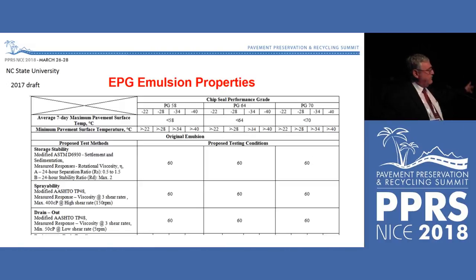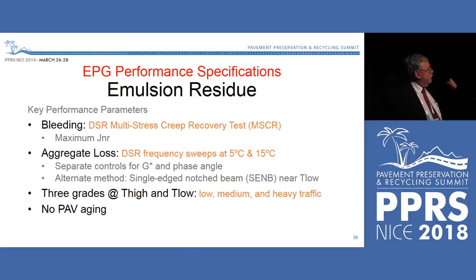And emulsion properties look something like this. Residue specifications, looking at bleeding, aggregate loss, how many grades do we need for traffic? This is a really big issue because we currently have modified grades, polymer modified and unmodified. We have 2 grades for any climate. The research is proposing we have 3 grades: low, intermediate, and high volume traffic chip seal emulsions.